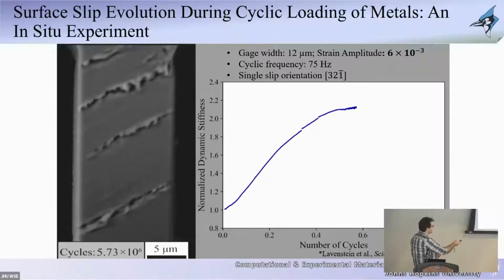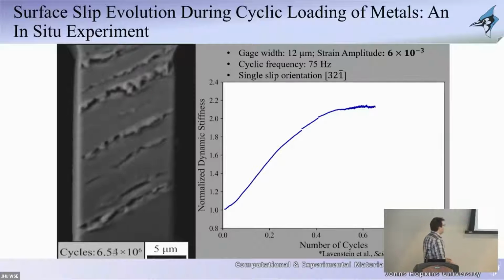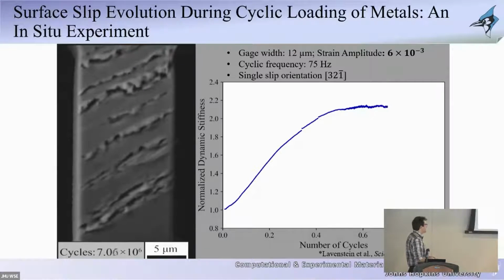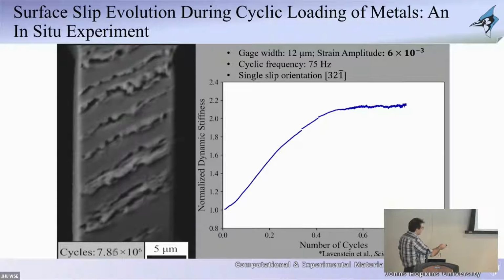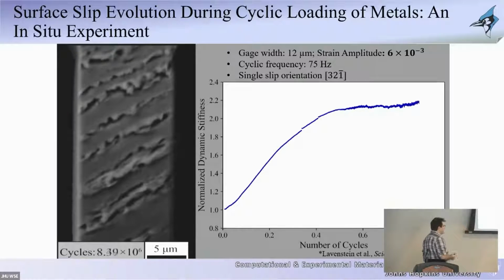Why along those specific lines? That relates to the orientation of the sample that we chose. Slip typically happens along specific paths in metals. So this is basically a line such that we know where the direction of that slip is likely going. Now what you're seeing on the right here is an interesting plot as well. So initially when nothing was happening, this was a straight hardening behavior. The material was hardening. You can see the dynamic stiffness was continuously increasing. This is something that is known classically in fatigue, that the materials harden when you cyclically load them, but without significant apparent damage on the surface.